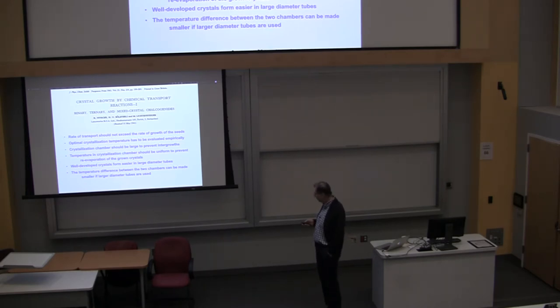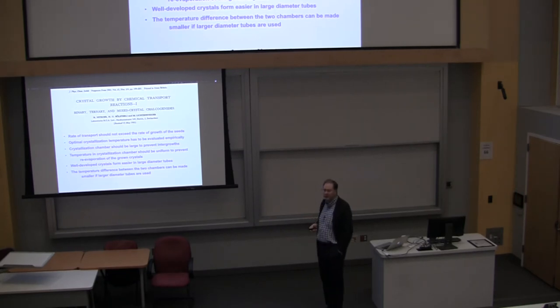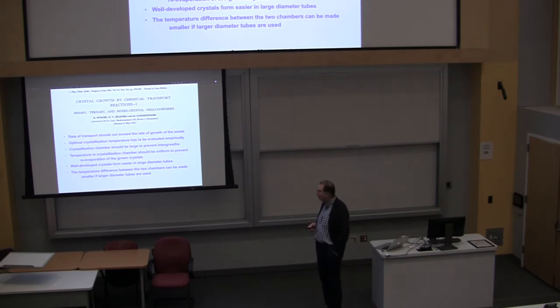There's a lot of rules of thumb. Basically, you don't want to go too fast. The rate of transport should not exceed the rate of growth of the seed, so you've got to adjust your gradient so you're growing at the right speed. There's a lot of empirical evaluation for your temperature and gradients. You want a nice large crystallization chamber with a nice uniform temperature. Bigger tubes are better generally, and if you're using a bigger tube, you probably want a smaller temperature gradient. But these are just rules of thumb that people have written down over the years.